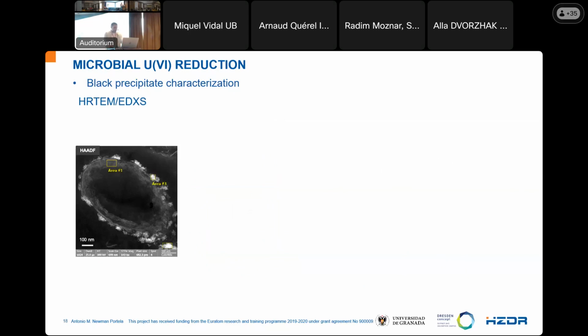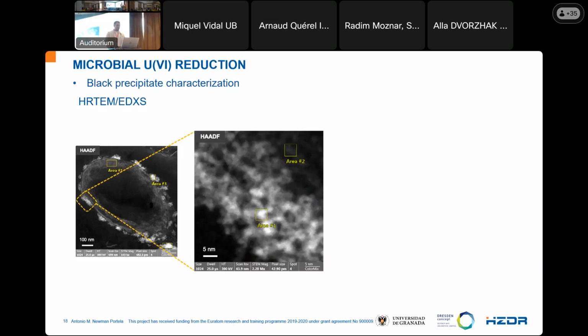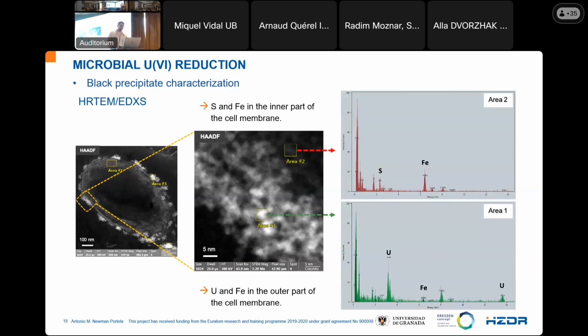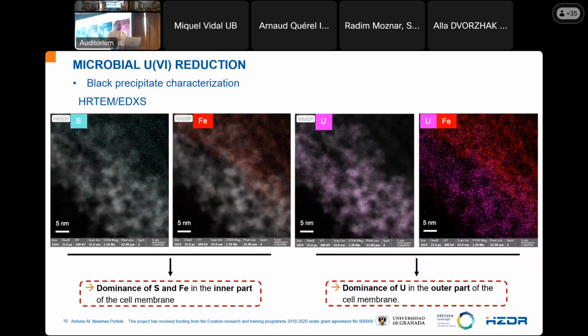To get an idea about the cellular location of the uranium and the crystallographic properties of these uranium-reduced products, we use high-resolution transmission electron microscopy, and we observed these bacteria cells and electron-dense accumulation around the bacteria cell. Using the EDX, we see the dominance of sulfur and iron in the inner part, and in the outer part we observe a dominance of uranium and iron. Based on the EDX data, we calculated the elemental distribution maps, and we confirmed the dominance of sulfur and iron in the inner area, and in the outer area the dominance of uranium.